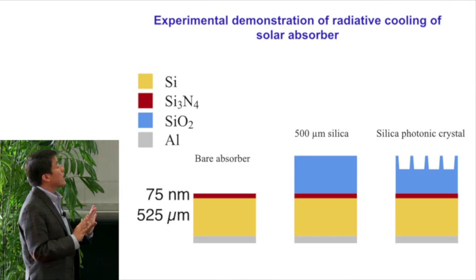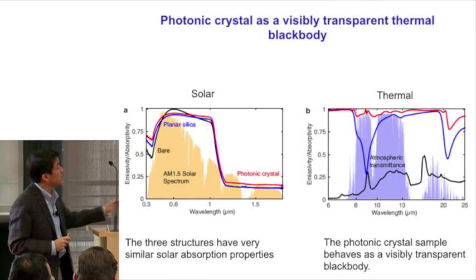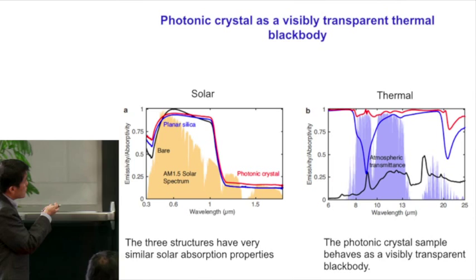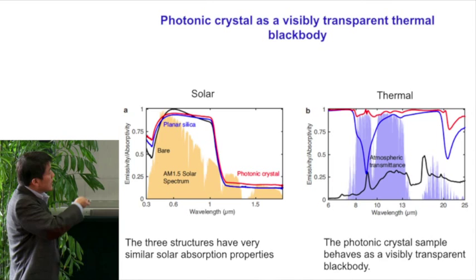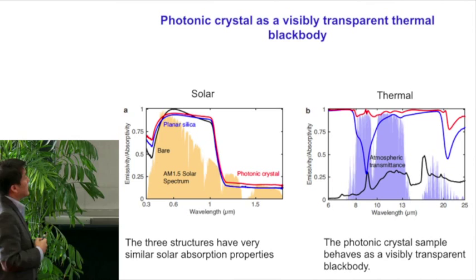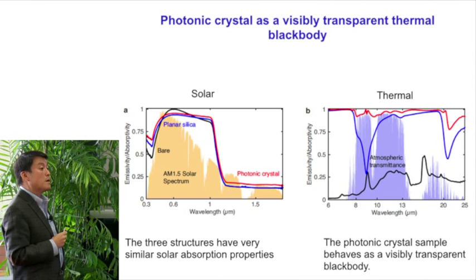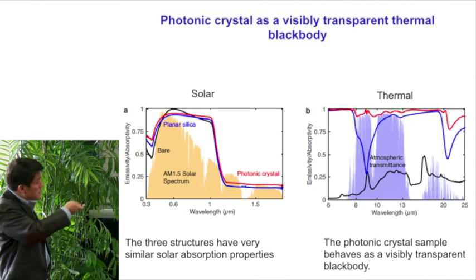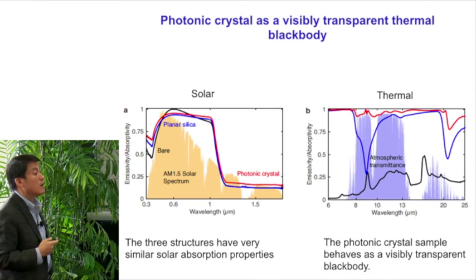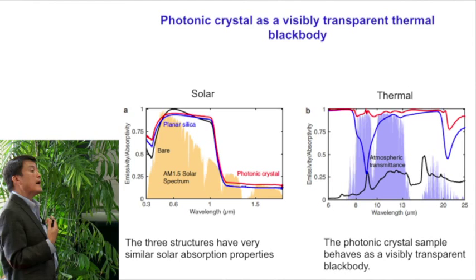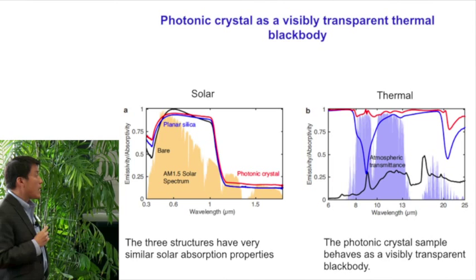First, we compare their optical and thermal radiation properties. And shown on the left here is the absorptivity spectrum of all three structures in the solar wavelength range. The yellow curve here is the AM1.5 solar spectrum. So what you see is a very typical absorptivity spectrum of silicon: above the band gap you have strong absorption, below you have weaker absorption, and the three structures have very similar solar absorption properties. In fact, the photonic crystal sample has a slightly higher absorption compared with the other two samples because of some light trapping effect coming out of engineering the silica surface.